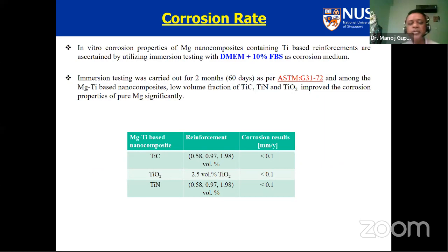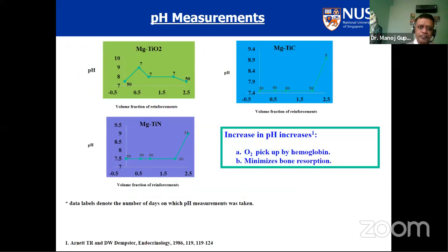Then we did the corrosion test in physiological medium, DMEM plus 10% FBS, and the result shows a very low corrosion rate at 0.1 millimeter per year, or less. When you talk with the surgeon and compute the healing time of the bone and cracks, they need something less than 0.2 mm per year. So these materials qualify from the corrosion point of view also.